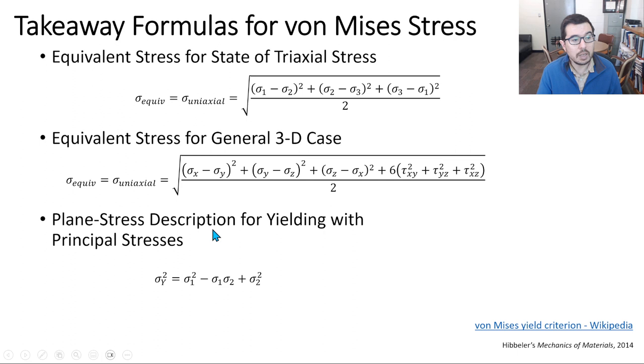This comes from the distortional energy theory that we've described up to this point, and it's a nice succinct condition. What does it say? It says we're going to have failure if this equation right here, sigma 1 squared minus sigma 1 sigma 2 plus sigma 2 squared, is greater than the yield strength squared. And this is another way to think of the von Mises criterion when dealing with plane stress. So let's do